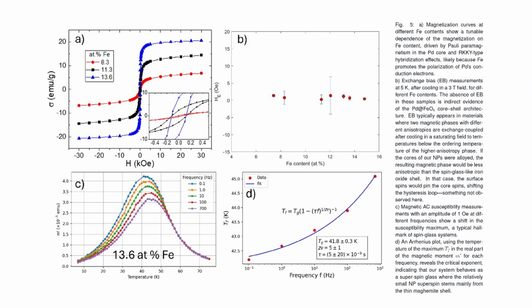We also measure the AC magnetic susceptibility with a small field amplitude at different frequencies. The peak in the real part of the susceptibility shifts with frequency, which is a hallmark of spin glass systems. And finally, from the Arrhenius plot of the freezing temperature, in our case T sub F, versus frequency, we extract the critical exponent, indicating that our system behaves as a spin glass.